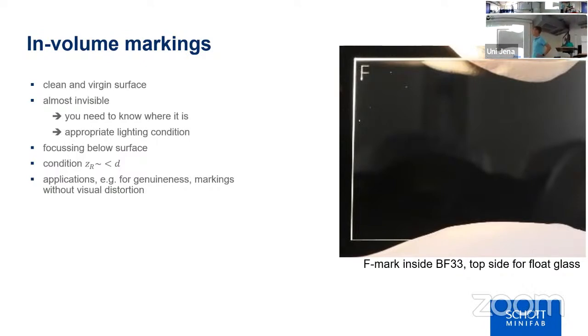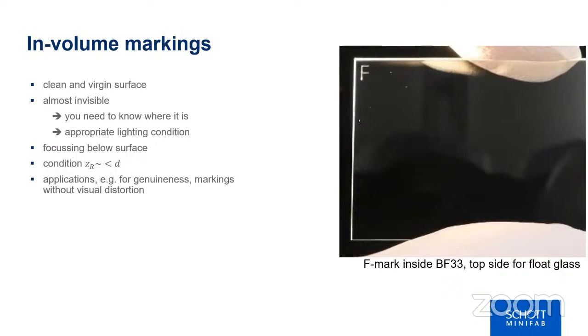Okay, maybe I start again with that slide. So what we're interested in is a marking of our glass. Borofloat has a top side and a bottom side due to the floating process. The bottom side lies during the fabrication on tin, and so it has a residual part of tin on the bottom side. So we have a bottom and a top side on the glass. And when we want to process the glass, we finally need to know. And therefore we use the so-called F mark.